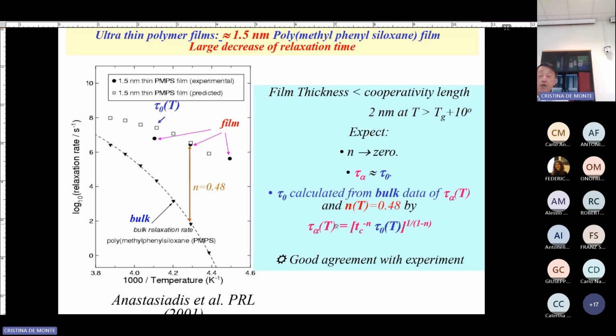You can calculate it because we know from the experiment the n value is 0.48. In other words, you can calculate from the bulk material, and you know the coupling parameter or the Kohlrausch parameter, and the n is 0.48. There's no fitting parameter. So use the equation and calculate that, and there you are. You find for three different temperatures, bam, you calculate that, it becomes these 3 points. It's in very good agreement with tau alpha. So you have proven it.